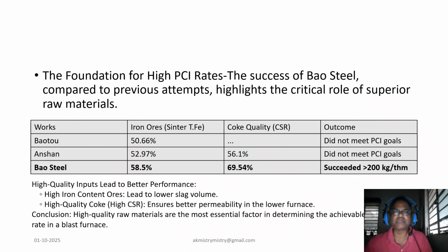So, why did Bao Steel succeed in sustaining a PCI rate over 200 kg per ton hot metal when previous industrial experiments failed? The sources point to one clear answer: the superior quality of their raw material. If we compare the inputs at Bao Steel with those at Baotou and Anshan, where earlier tests did not meet their goal, the differences are stark.